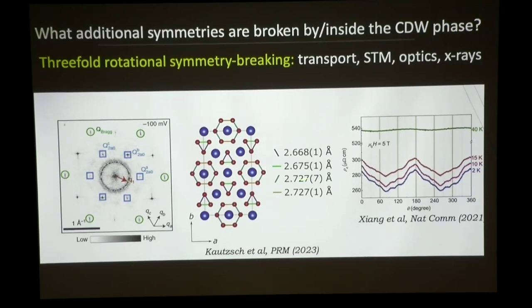By a huge number of measurements, STM, optics, and X-rays, you can show that the charge density wave breaks rotational symmetry. What that means in this particular Fourier transform is that one of these peaks, this one and this one pair, is more intense than these other 2 pairs. And just by being more intense in one particular direction, you've broken rotational symmetry.